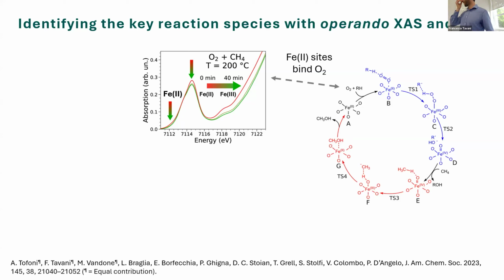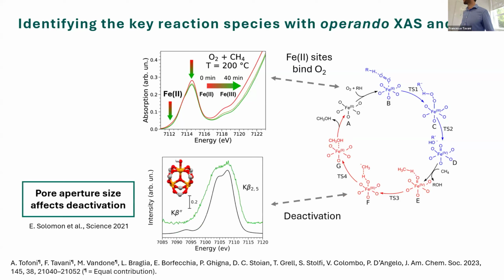Progressively, we constructed a hypothesis for the mechanism. There is a very small amount of methanol that is produced, very small. We track this with real-time mass spectrometry. And at the end of the day, the XAS data collected on the post-reaction catalyst, which is shown in green, allowed us to hypothesize that when the catalyst deactivation occurs, because it does occur, it leads to the presence of trimeric units which are hydroxylated. And this seems to hint to the hypothesis that the pore aperture size, the size of the pores in MIL-100, critically affects deactivation.